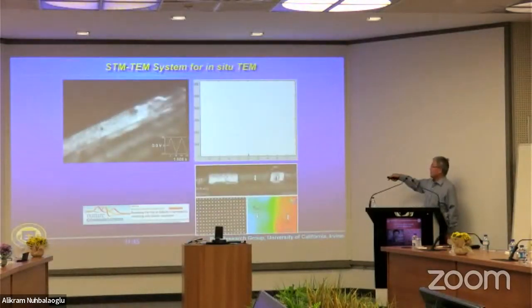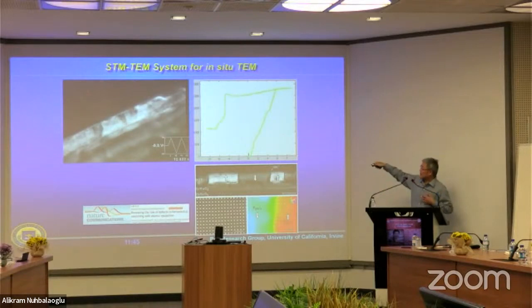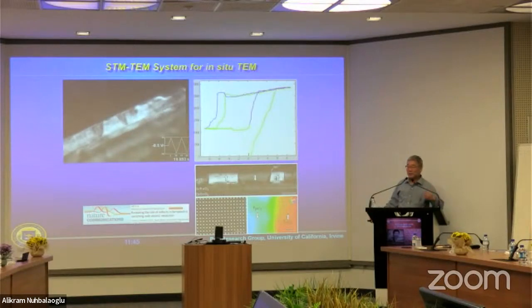So, okay, now this is good. You see, this is the first in situ switching of ferroelectric materials. This is an STM tip. This is the bottom electrode, which is also an oxide, structurally matching very well with the substrate and the ferroelectric film. So you can see that when the electric field is applied, up positive and down negative, up and down, you can see the nucleation starts from here, where the field is strongest, and then it propagates further. And then this is like how a ferroelectric memory device works.